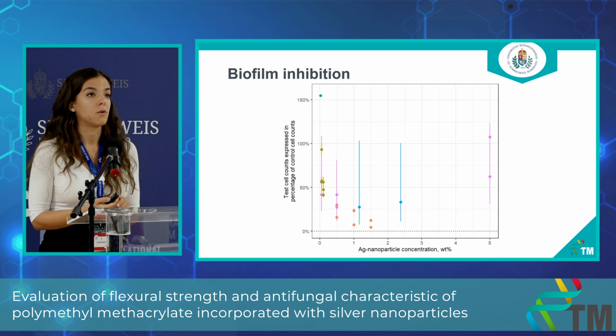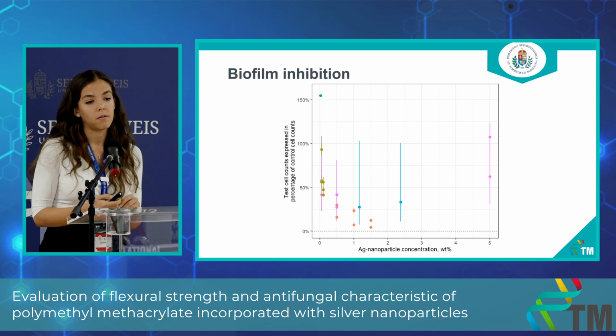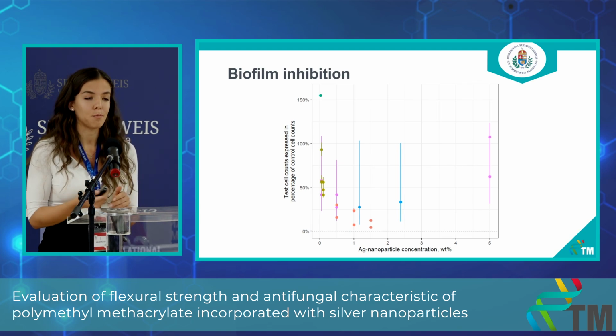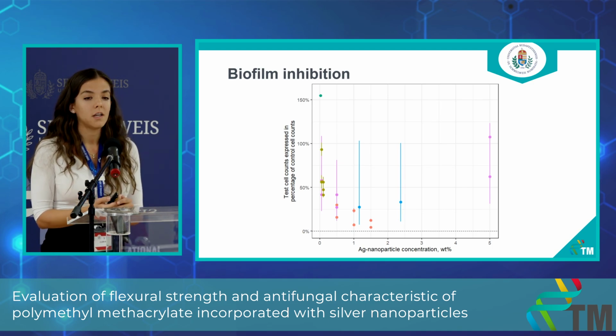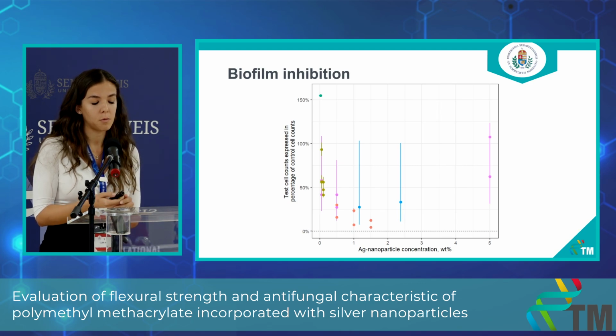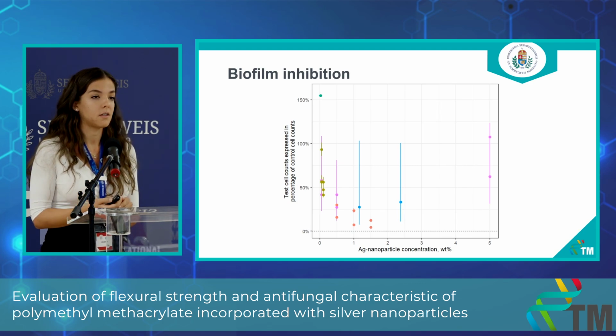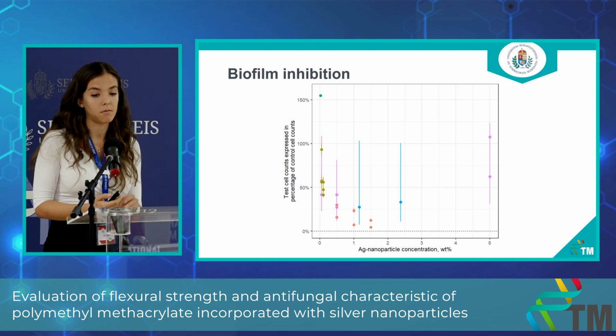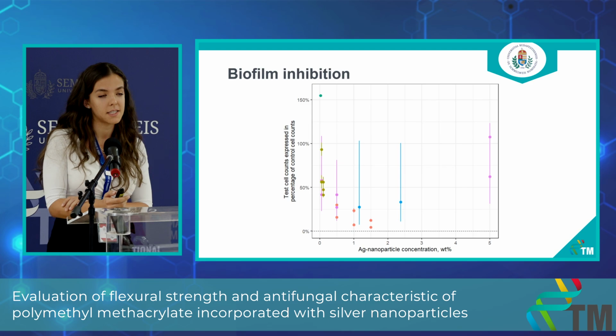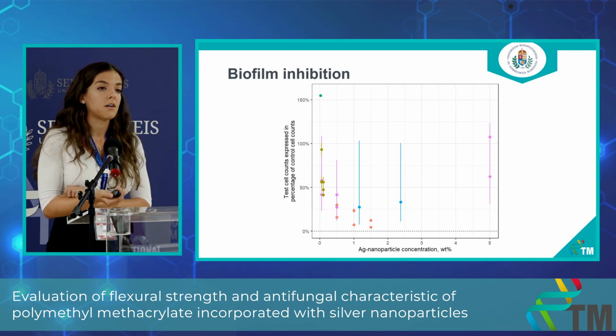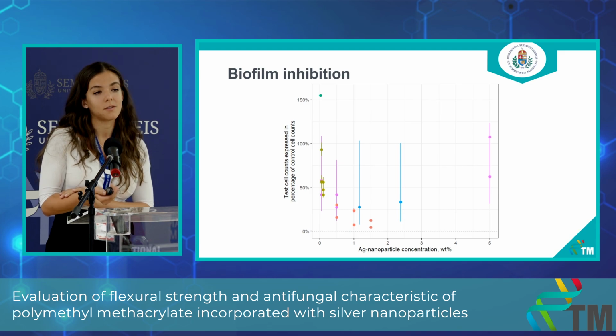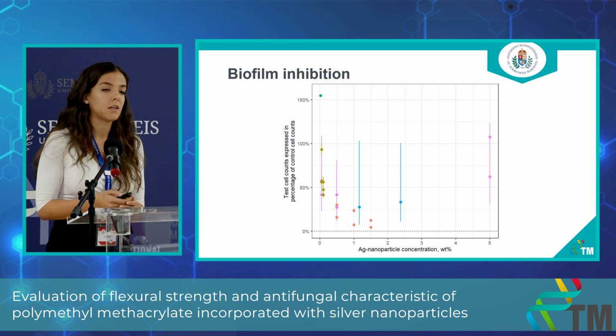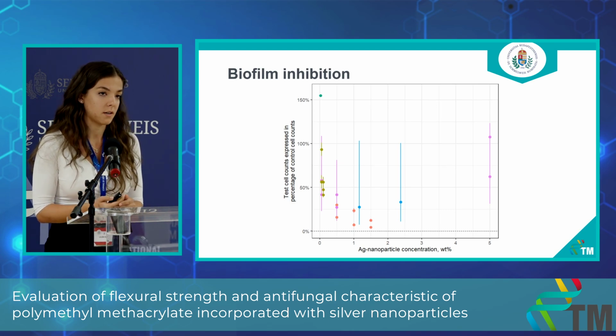Let's move on to the last outcome, which is the biofilm inhibition. The biofilm formation shows the number of cells on the samples which are adhered to the surface of the samples, and in this case we have the test samples which were incorporated with silver nanoparticles, and there was the control group which was not incorporated with silver nanoparticles. On this graph you can see the ratio of the cell count of the test groups to the control group in a percentage. And on the horizontal axis you can see the silver nanoparticle concentration.